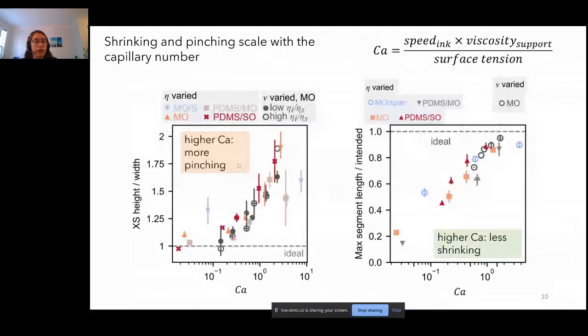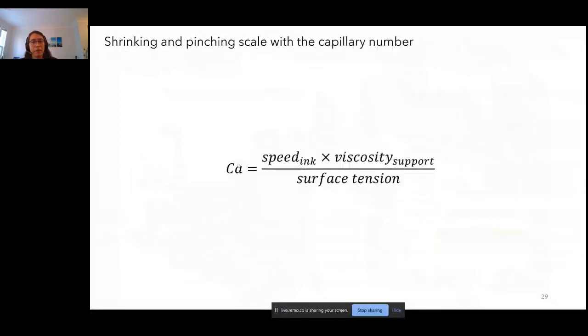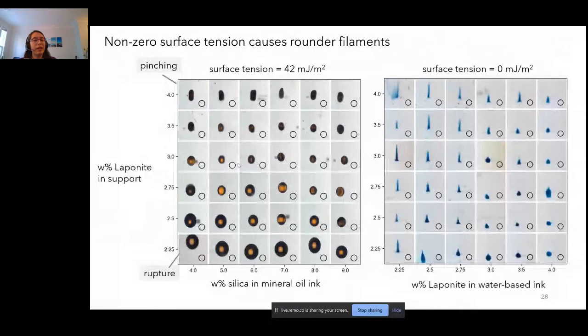So here you can see that as we increase the capillary number, we get a taller cross-section height over width. And so that's telling us that we get more pinching as we go to those higher capillary numbers. So that's less than ideal. However, these aspect ratios are not as tall and narrow as the water-based inks that we saw. And I'll also note that when you have these oil-based inks, you don't get any of the sharp edges or flat bottoms that you see in these water-based inks. So we always have rounder filaments, which is going to be an improvement for our surface roughness.